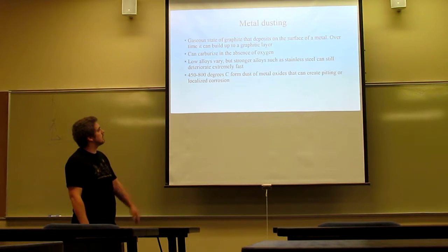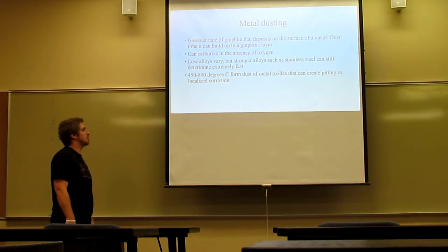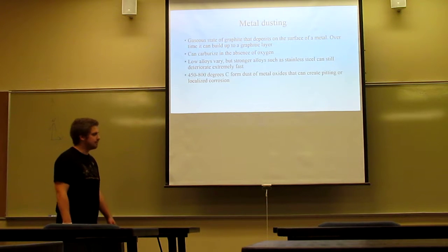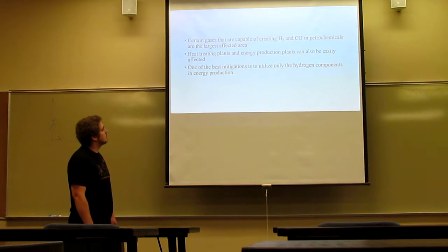Low alloys vary depending on this, but stronger alloys such as stainless steel can still deteriorate pretty fast. The average temperature is about 450 to 800 degrees Celsius for the metal oxide to create pitting or localized corrosion. Certain gases that are capable of creating H2 and carbon dioxide in petrochemicals are the largest affected areas. The heat treating plants and energy production plants can also be affected, hence the high heat. One of the best mitigations for this is to utilize only hydrogen components in the energy production.